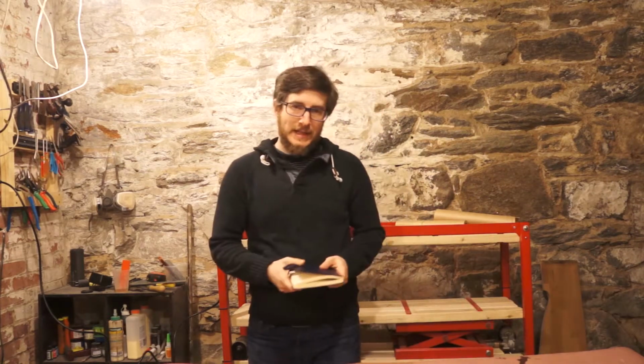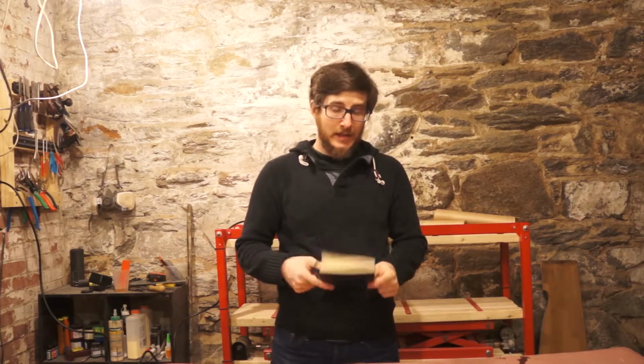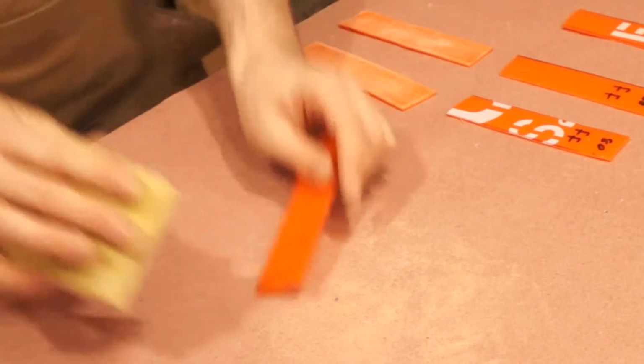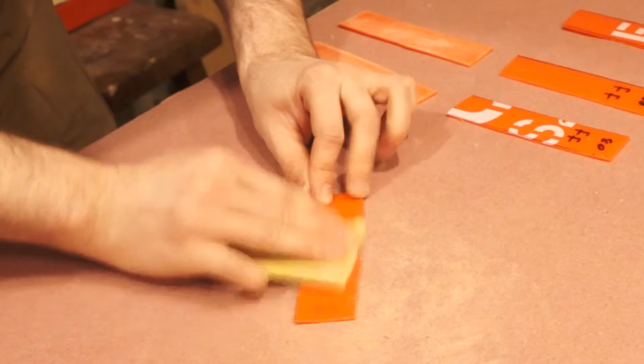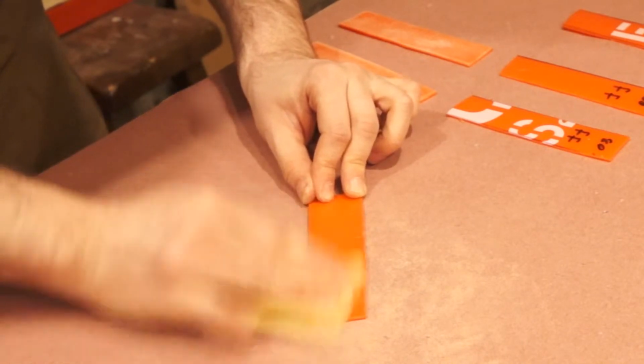Well, I went back to the tape, and I figured out exactly what happened. Did you catch it? Here's a video of me sanding the piece that I marked for 80 grit with 400 grit sandpaper. So that last set of examples that we tested, I had the 80 and 400 grit switched, which is why the ratings were a reverse of the trend that we were seeing in the other sample sets. Let's take a look at the final verdict here.